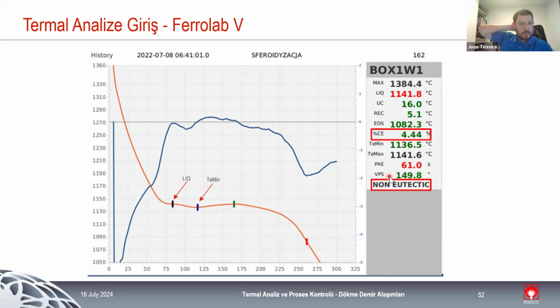VPS is also an important value for us to study in the thermal analysis. It's an indication of the end solidification step. So it's this angle that we see here that is related to the end of solidification.